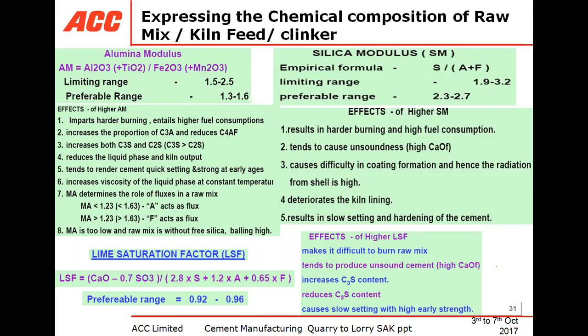Then the silica modulus. It results in hard burning and high fuel consumption. If the silica modulus percentage becomes high, it results in harder burning and consumes high fuel. It tends to cause unsoundness because of the high silica modulus. It causes difficulty in coating formation and hence the radiation from the shell is high. Then it deteriorates your kiln lining. If the silica percentage is high in your raw material, it is quite abrasive in nature and disturbs your kiln lining. Again, if the silica modulus percentage is higher, it hampers your setting. Your setting becomes slower and slower.